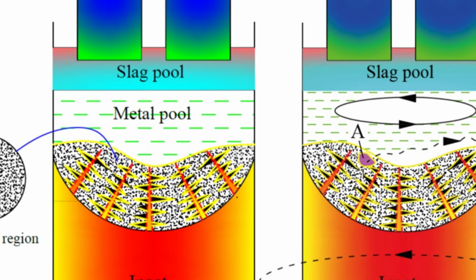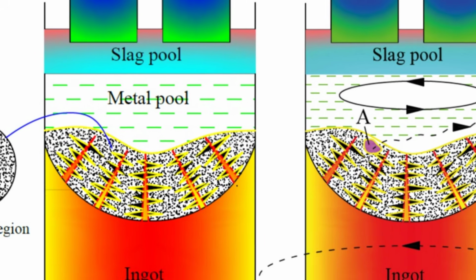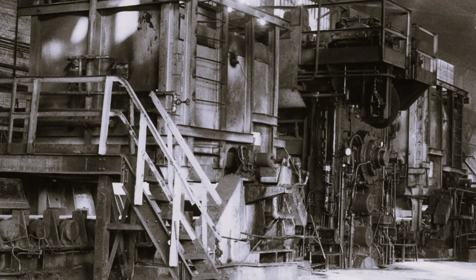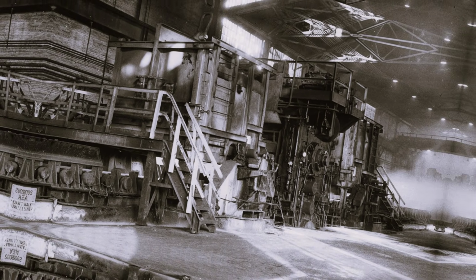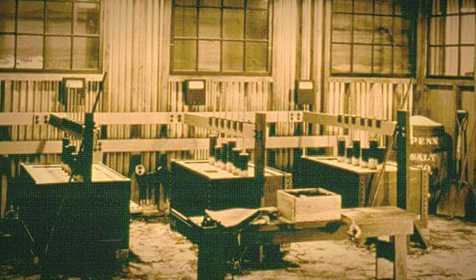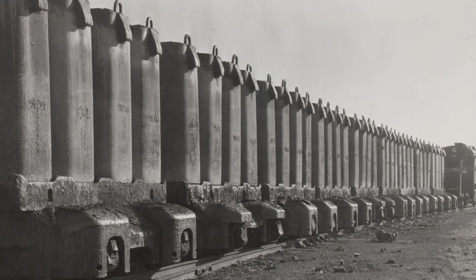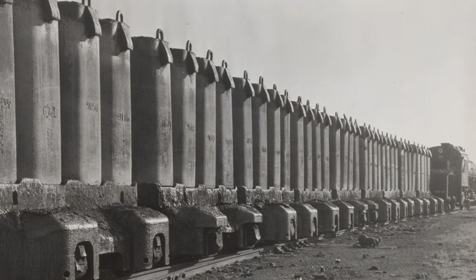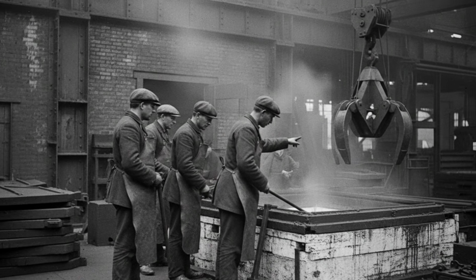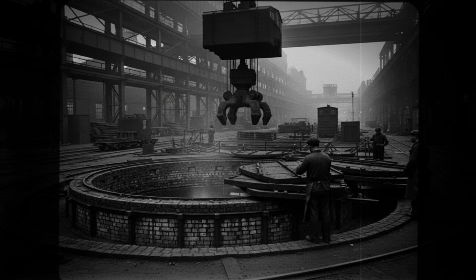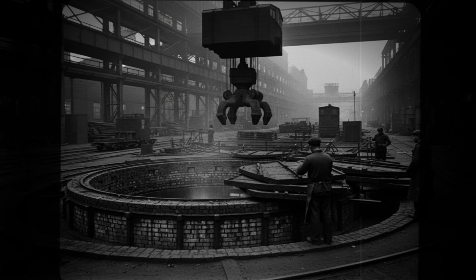An ingot that had not reached uniform temperature through its entire cross-section would reveal that fact immediately, either by splitting under the rolls or by producing a finished section with internal defects that would only become visible after the steel had already been shipped. The pit was the quality control step that no downstream process could substitute for.